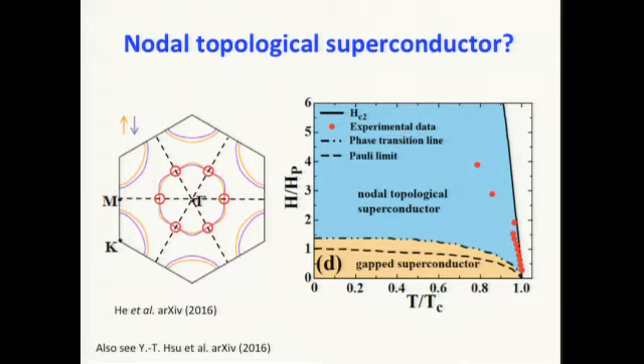But that may not be the major effect, because the Fermi surface gets changed a lot when you go from niobium selenide to tantalum selenide. In niobium selenide, the spin-orbit splitting is still very small compared to the bandwidth. The bandwidth is about 1 eV, the spin-orbit splitting is about 0.1 eV. But in the case of tantalum diselenide, the spin-orbit splitting is half an eV, and the bandwidth is also 1 eV. So basically, it's quite a dramatic change compared to niobium selenide. I think the strength of the electron-phonon coupling is quite much modified.